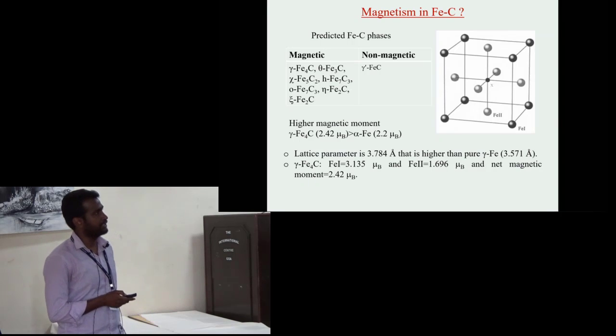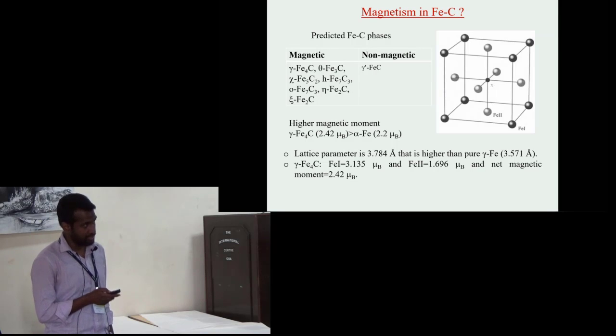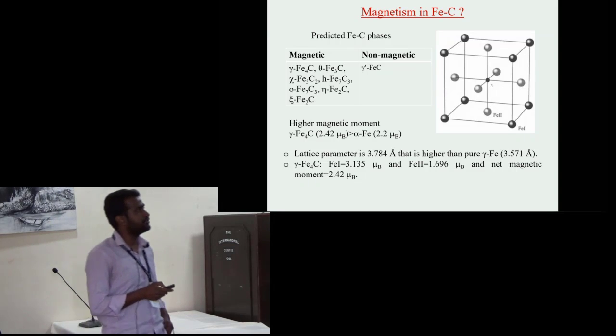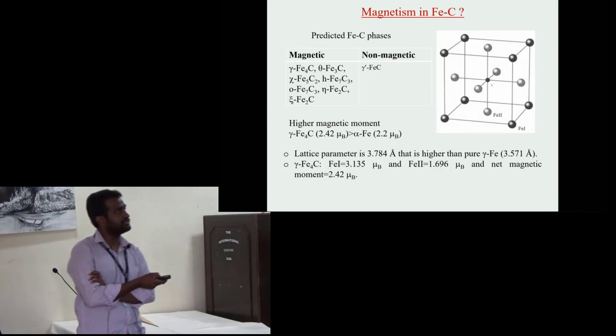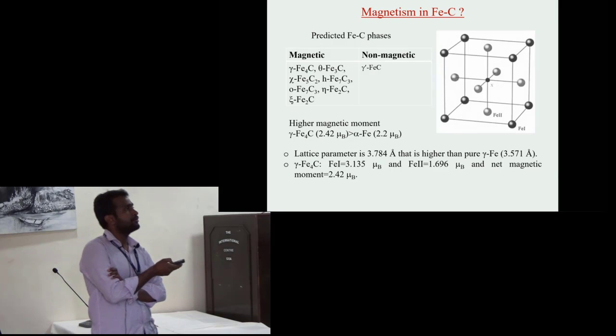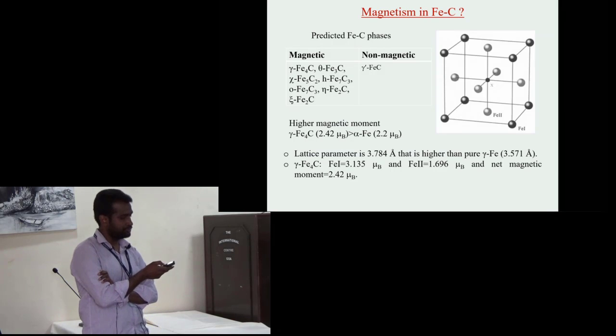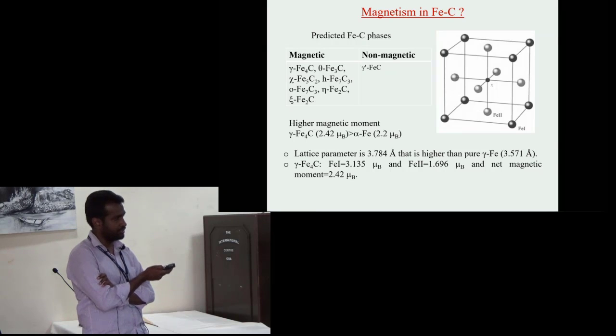The lattice parameter of gamma iron is 3.57 angstrom. When carbon occupies the interstitial position of the iron lattice, the lattice parameter increases around 6 percent. With this increase in lattice parameter there will be two iron sites: the corner site is an interstitial site and the face center site is a bonding site. These two sites have different magnetic moments, and the resulting magnetic moment is higher than the magnetic moment of iron.